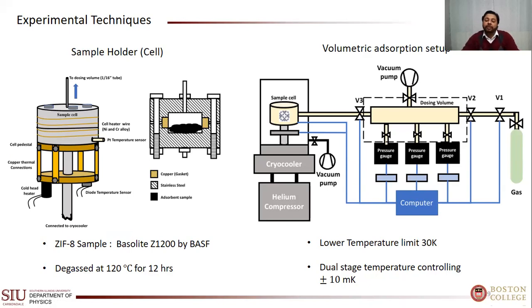Most of the isotherms are done at really low temperatures so that the gases are slowed down and we can see a clear interaction between the materials and the gases. This experiment usually takes almost a month to take all the data we need, and it has to be kept at really low temperatures, even down to 30 Kelvin, to see the fundamental interactions between the material and the gases. So that's the uniqueness of our experiments, where the physics comes in, whereas chemists don't usually use such low temperatures, and we can easily characterize the material and get most of the fundamental interactions.